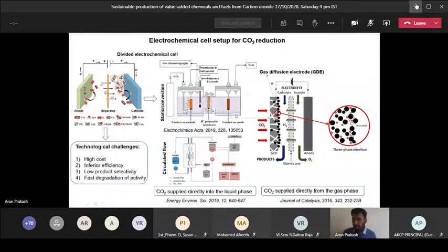Why are copper-based catalysts mostly used for CO2 reduction? Because copper is the only metal which has, you can observe the scale on the bottom and also on the top, on the left. The scale on the bottom gives you an idea about the adsorption energy, delta E of hydrogen adsorption, and this one gives you delta E of carbon monoxide adsorption. Copper is the only metal, so that's why we put the cross here, and you can observe the cross for copper, that is around 0.2 or something. Whereas if you see the other metals, they are mostly negative.